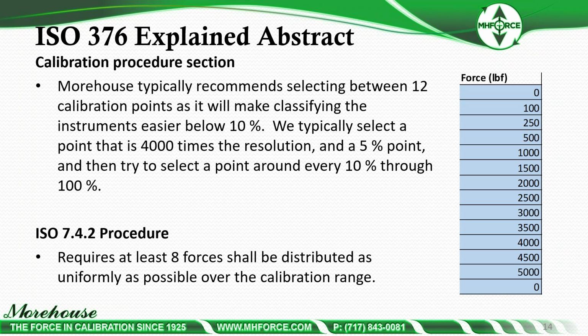We do this because if the instrument does not meet class 00 at 2%, it's not going to meet it if we don't take that 5% point until probably 10%. And from that 2% to 10%, you cannot use it in the class 00 range. So we take a 5% point, and in most cases, the instrument will meet at the 5% point if it's a good load cell or good force indicating instrument.